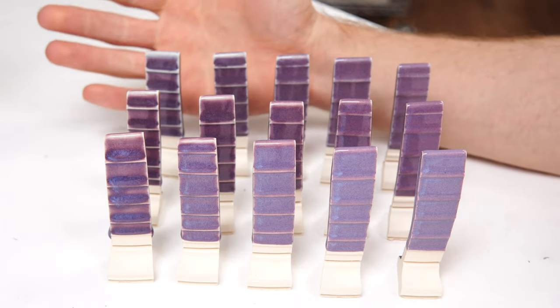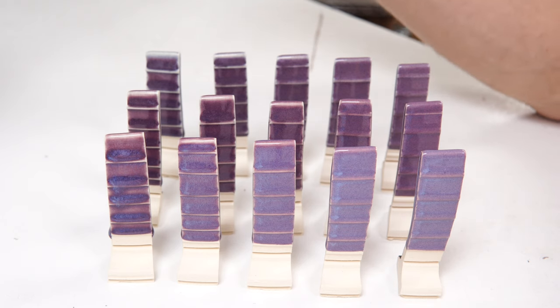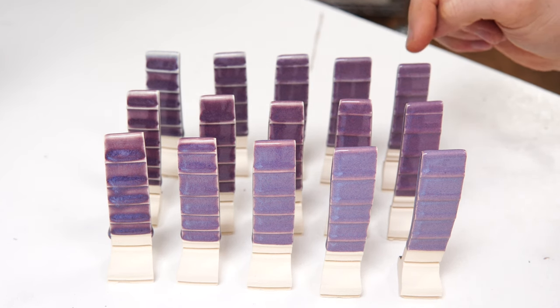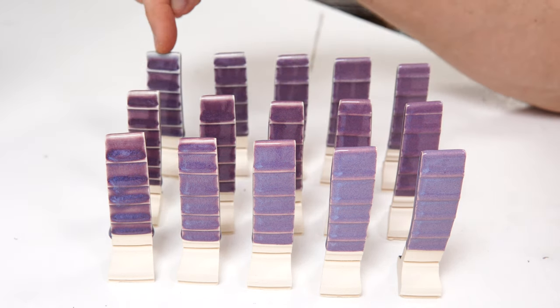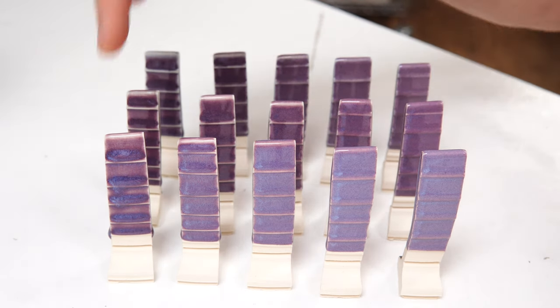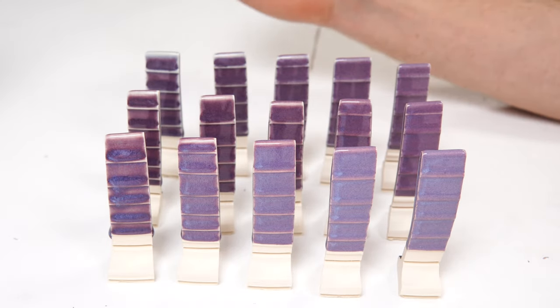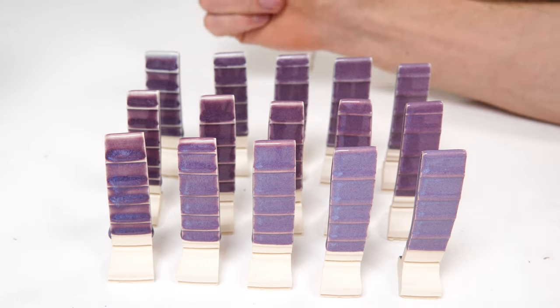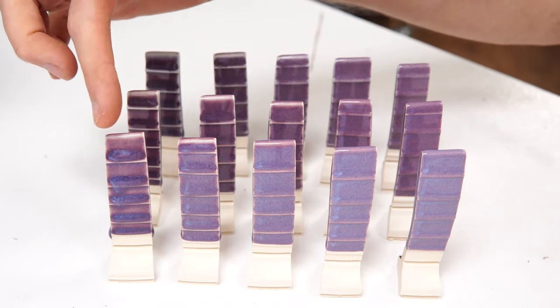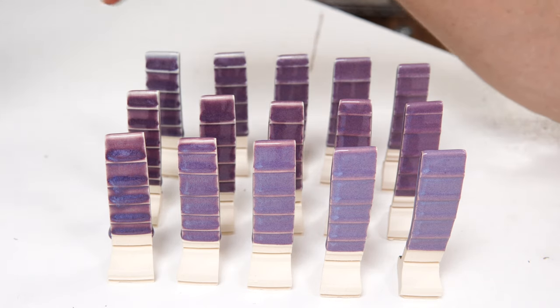That's basically how I would go about doing a test where I had four corners and I wanted the in-between stages, but it would work just as well if you had colorants. What I'm considering doing now is picking one of these top recipes, possibly the top corner, and I'll do a version where I have tin and titanium, tin and titanium and chrome, tin titanium chrome and cobalt, and tin titanium and cobalt. So you'll get red, blue, purple with incremental steps. I want to change some variables but not all of them. I think the titanium and the tin are necessary to give this glaze any characteristics.